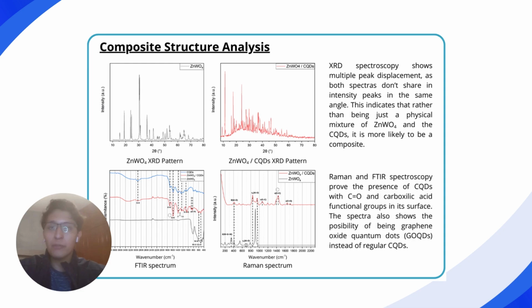In X-ray diffraction, when comparing the maximum peaks of the zinc tungstate patterns with the composite ones, we can see that both spectra basically don't share almost any relevant peaks at the same angle. This may be due to the amorphous organic matter present in the composite, thanks to the carbon quantum dots. Now, it is difficult to identify the corresponding zinc tungstate peaks in the composite. However, it's reasonable to assume that the crystalline structure was modified and there was a displacement of the peaks. Whether it's towards left or right, we cannot determine yet. But this indicates that it's maybe a different crystalline structure and not just a physical mixture.